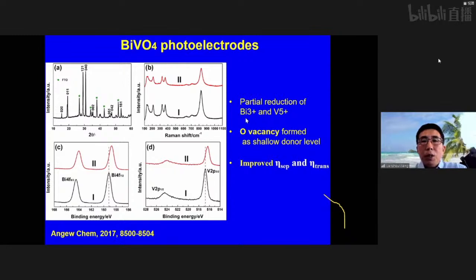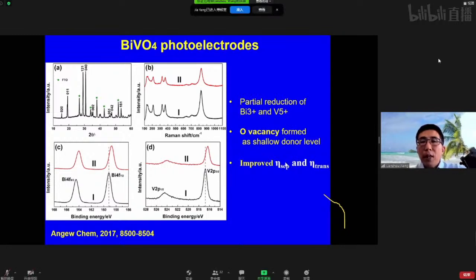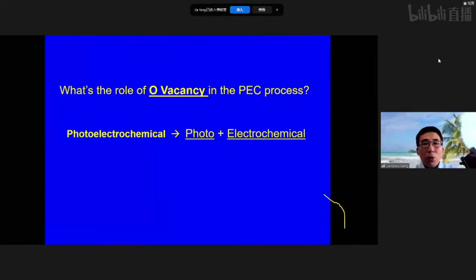In this case, bismuth was reduced from 3+ to 2+, and vanadium from 5+ to 4+, and this generates some oxygen vacancies. The oxygen vacancy can behave like a shallow donor level and improve the charge separation and transfer properties in the system. This implies that oxygen vacancies can play a very significant role in the PEC water splitting approach. So we wanted to understand the oxygen vacancy more thoroughly